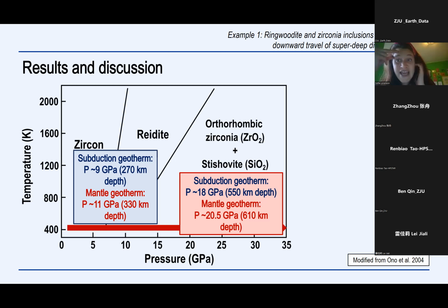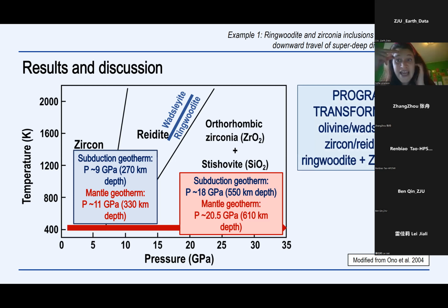and 610 kilometers. And if we consider that wadsleyite will transform into ringwoodite at a depth of about 525 kilometers, these things suggest to us that probably the multi-phase inclusion that we observe in our diamond is the result of a progressive transformation of a former inclusion composed of olivine or wadsleyite plus zircon or reidite.